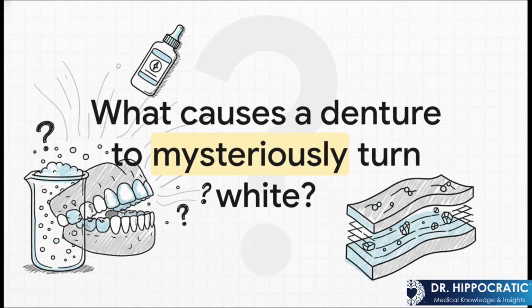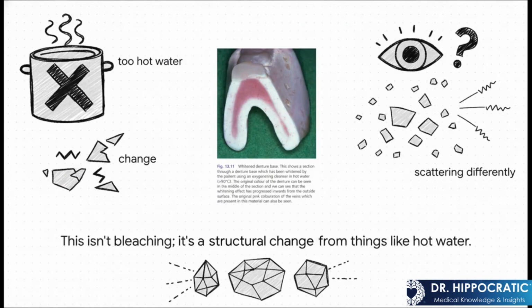This brings us to something that people who wear dentures sometimes notice. A denture can start to get these white patches, and a lot of times, people think their cleaning solution is somehow bleaching it. But is that what's really going on? Nope, not at all. Have a look at this cross-section. That whitening you see isn't a color change, it's a physical, structural change deep inside the resin. Things like using water that's way too hot can mess with the internal structure. This creates what scientists call a refractive index mismatch. Basically, the light passing through the material starts to scatter all over the place, which makes it look white to our eyes. It's a really cool optical illusion based in material science, not a chemical reaction.